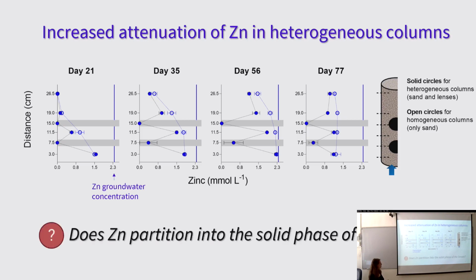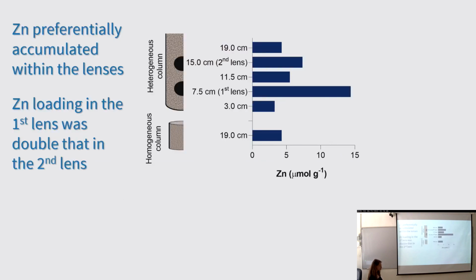That raises the following question: does zinc partition into the solid phase of the lenses, or does it simply bypass them? For that, we're going to transition now into solid phase concentrations of zinc. Here we're looking at solid phase zinc in a heterogeneous column on top, and an average value for a homogeneous column below. This shows us that the zinc is indeed being retained into the solid phase.